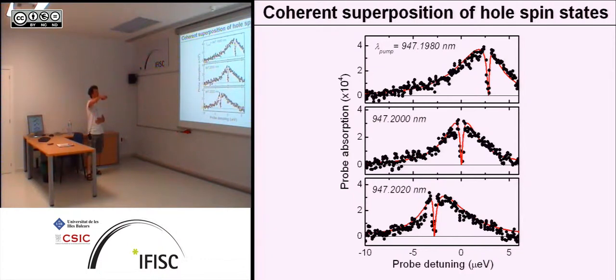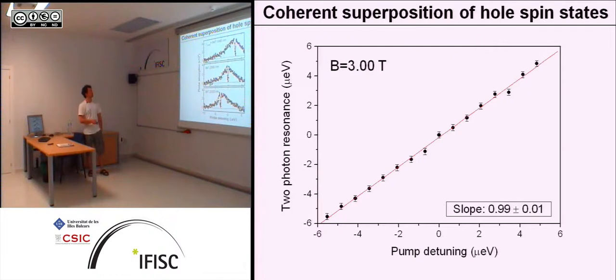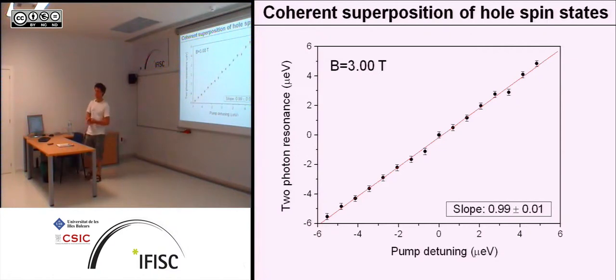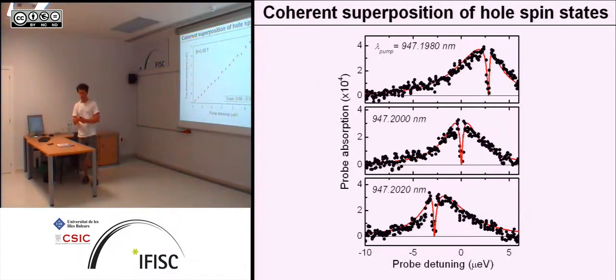So here we are positively detuned, and the maximum is next to the dip instead of in the middle. And we still have this narrow dip. Here we have 0 detuning, and here we have negative detuning. So this pretty much corresponds to the textbook lambda system model. Just what you have to add is this convolution of the excited state. And this is some proof that we really deal with coherent population trapping and not something called Autler-Townes splitting.